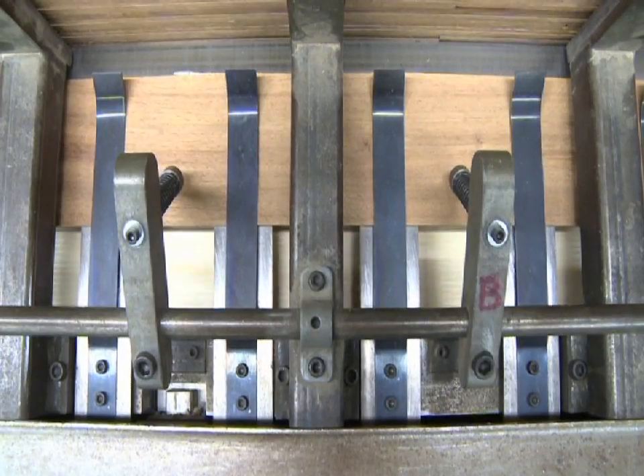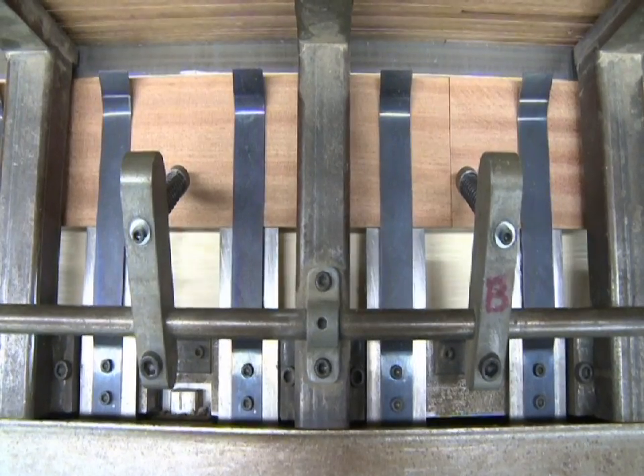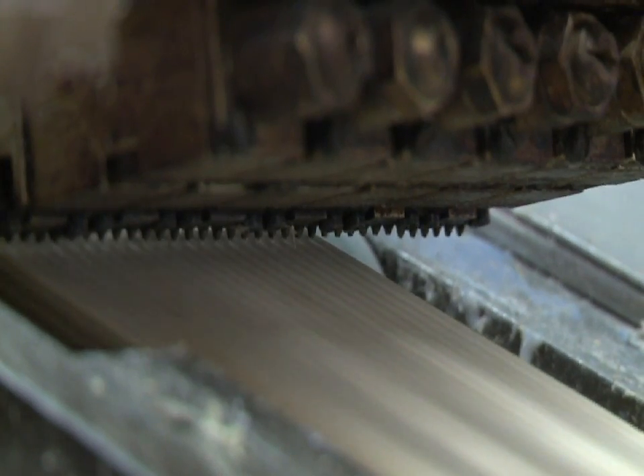The adhesive bond between the top lamella and plywood core is very important to ensure success of Vintage's crafted engineered flooring. Only polyurethane-based adhesives are used to ensure the highest quality bond between plywood and lamella. The adhesive is applied to the plywood in a hot melt form using an extruder.